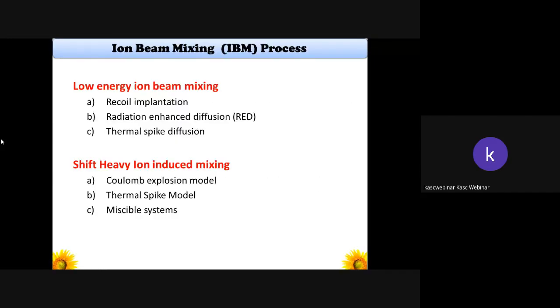And another technique involving ion beam processing is called ion beam mixing. Simply, we may call it the IBM process. This IBM is also achieved by using low energy ion beam mixing and high energy ion beam induced mixing. In low energy ion beam mixing, recoil implantation is also possible, that is, the dopant or doping profile. Then the second one, radiation enhanced diffusion and thermal spike diffusion are also possible. With respect to swift heavy ion induced mixing, it may also support the Coulombic explosion model and a spike model in insulators and thermal spikes model in metals and semiconductors. And this can be used for immiscible systems also, to make them miscible.